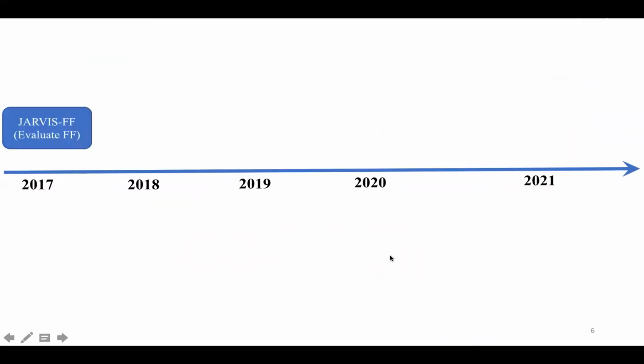So as I said, we started in 2017. We actually started with JARVIS-FF, the Jarvis force field, to evaluate classical force fields or interatomic potentials. For that, we used the Materials Project energetics and elastic constant data to check whether a classical force field is suitable for particular applications or not. Then we saw that there was a need for a 2D materials database. So in 2017, we developed a lattice constant criterion, and then we used that on the Materials Project data set. And then we discovered around 1,000 new 2D materials, and we validated them using exfoliation energy calculations with the OptB88vdW functional in density functional theory.